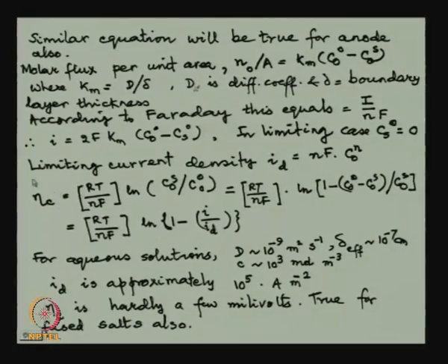Now, what is then the value of the overpotential? We can make substitution and get an expression that the cathode overpotential is given by an expression, which is a function of current density and limiting current density. Now, for aqueous solutions, diffusion coefficient generally has this value, delta, that is the boundary layer thickness, has about this value, and concentrations are generally 10 to the power 3